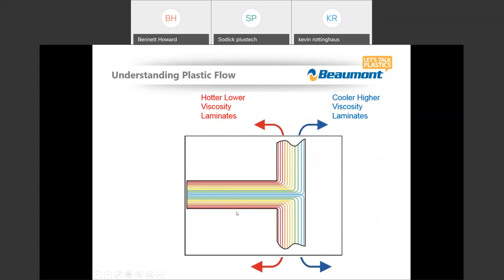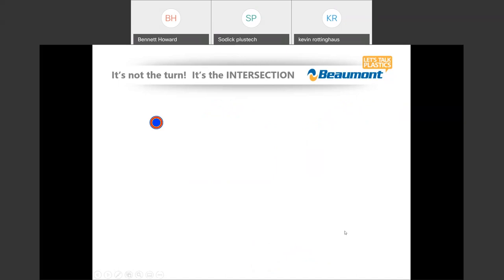So where does the problem occur? The problem occurs at intersections. That annular ring comes up to the intersection and those laminates split non-uniformly. You can see with this colored scale here, the higher shearing laminates stay within themselves. Again, they're not going to retain turbulent flow coming up to this intersection. Plastic doesn't come up into this intersection, tumble around and mix up and then continue along its way. Those laminates simply stay within themselves. The laminates in the outside perimeter stay within that laminate, and the laminates in the center stay within those laminates of flow. So now we end up with all our higher shearing, less viscous, hotter plastics on one side of our runner, and cooler, more viscous laminates on the opposite side. So again, it's the intersection.